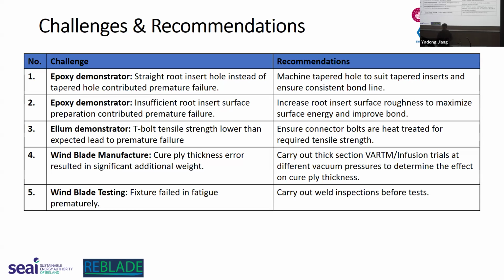Then in terms of the Elium demonstrator, we saw that the failure again was in the T-bolts. The reason behind that was the tensile strength was lower than expected, so we should have preheated or heat treated the connector bolts to try and improve the tensile strength. So that's what we do going forward, and that's what we did on the 13-meter blades. We learned from that demonstrator test. We got the full-scale T-bolts heat treated, and you can see that there was no sign of failure, even though it was loaded up to 160% of the design load.